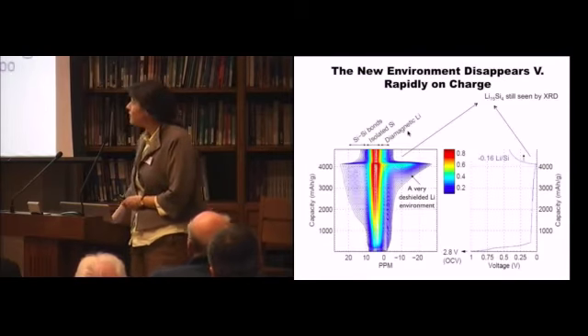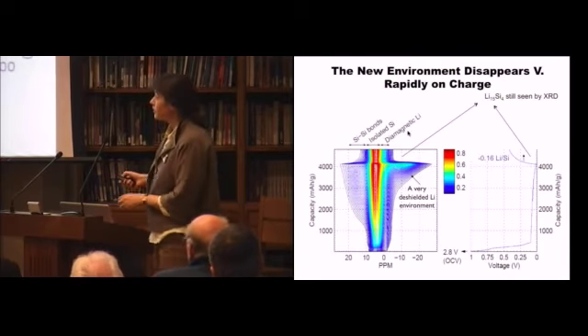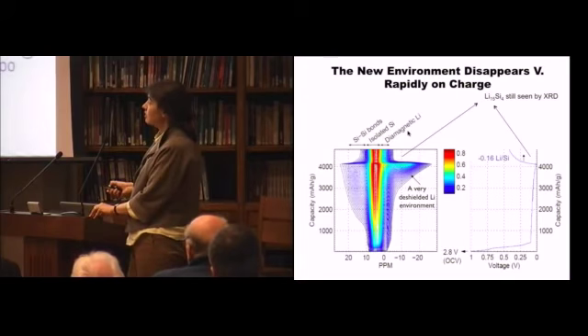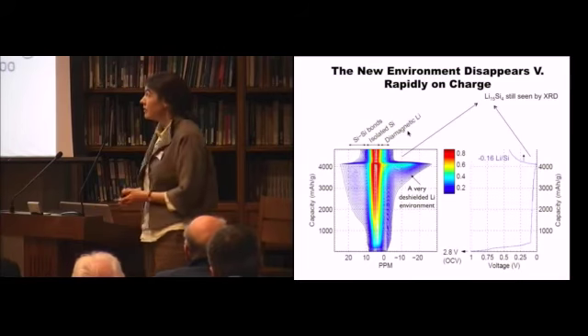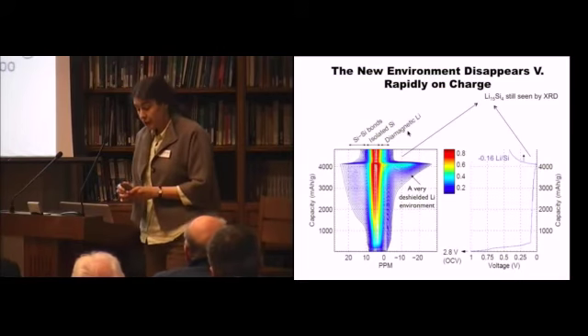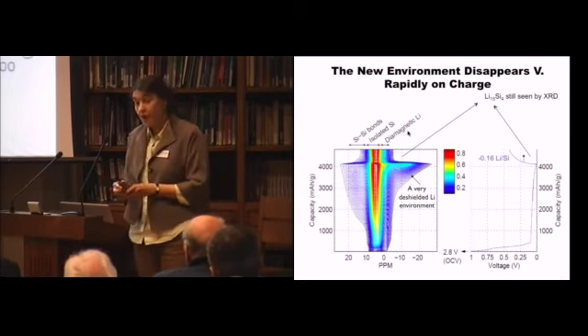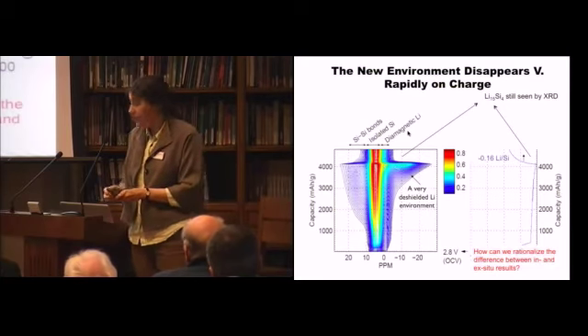So if you didn't see that, it's easier to see on a contour plot. So here's the reaction of the carbon, here's the formation of the clusters, here's the formation of the isolated ions, but you're also seeing this very de-shielded lithium environment. So the question you then have is, is it just we can't make good batteries? Are we just missing something?